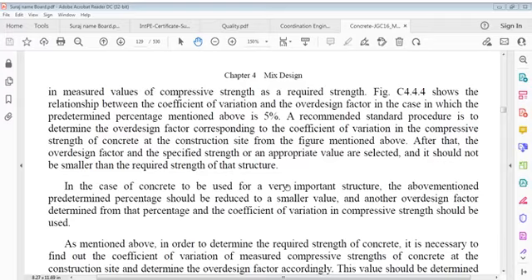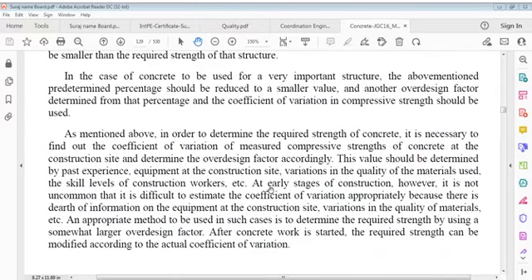Required strength. The figure shows a relationship between coefficient of variation and over-design factor in cases in which predetermined percentage mentioned is 5%. A recommended standard procedure is to determine over-design factor corresponding to coefficient of variation in compressive strength of concrete at construction site from the figure mentioned above, after which over-design factor and specified strength or an appropriate value are selected, and it should not be smaller than required strength of that structure. In case of concrete to be used for very important structure, this predetermined percentage should be reduced to a smaller value, and another over-design factor determined from that percentage and coefficient of variation in compressive strength should be used.